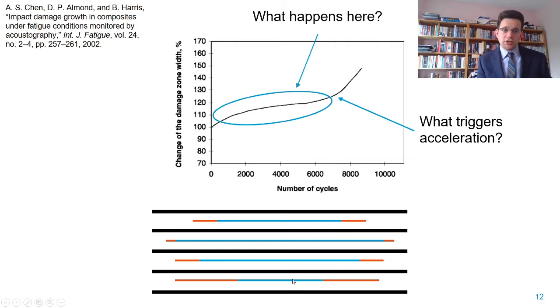This gives the illusion of a plateau where not much growth is occurring, when there actually is a lot of growth happening. We can also imagine that once all these delaminations get similar in size, they might suddenly all start growing much faster—and that could be the sudden acceleration we observe. For the moment this is a hypothesis, but hopefully as a community we can investigate and get a better understanding of what is actually going on.